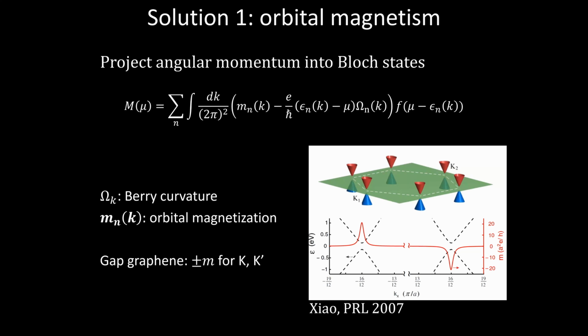Now that orbital moment will be equal and opposite in the 2 valleys, but at least it's a degree of freedom which is very much Ising-like. This is obviously very anisotropic. You can think about it as a physical current that's flowing in the plane. In a monolayer of graphene, this current flows in the plane, but it does not flow out of the plane, right? This is an orbital current. Okay, so that's our degree of freedom that's going to be important: if you can gap out these Dirac cones, you're going to get a large orbital moment.